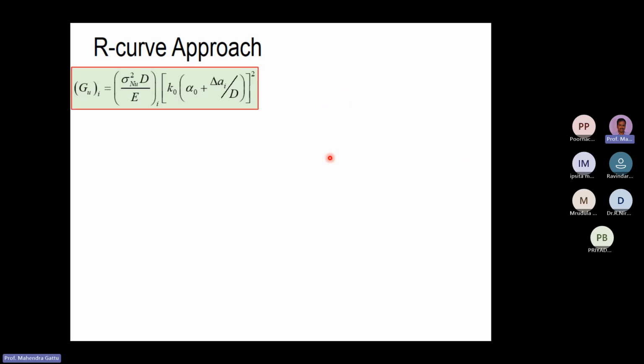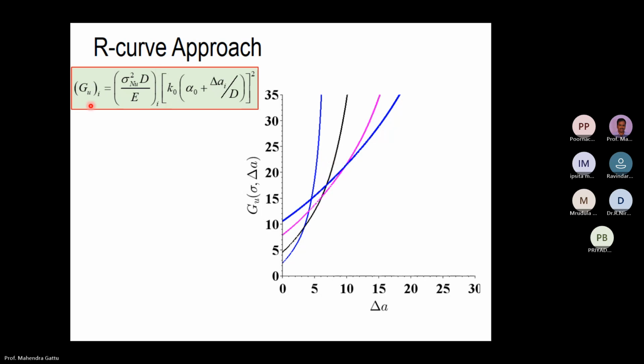So this is the theory of quasi-brittle fracture mechanics. There is something about the R curve, the crack growth resistance curve, which I think might not be possible to explain fully, but I'll see. Here we have the expression for the fracture energy G, which is given as K_SE squared by E. For K_SE we can use the equivalent elastic crack model and put sigma N squared d k naught of alpha naught plus delta A by d, whole squared.